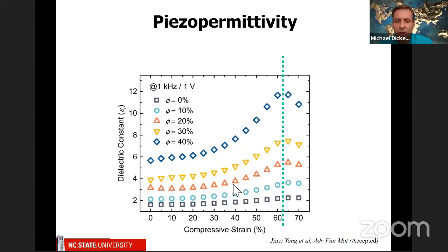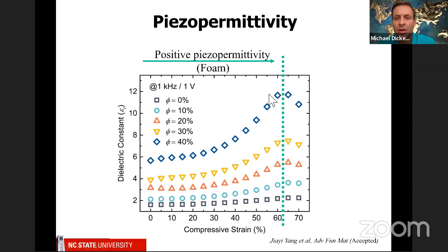Now, this initial change is, we call it piezo permittivity. It's a fancy word to say that the dielectric constant is changing and it's positive, it's increasing. You can see that because of the shape. And it does this for a very simple reason. Just because you have a foam, you're displacing air and replacing it with polymer.